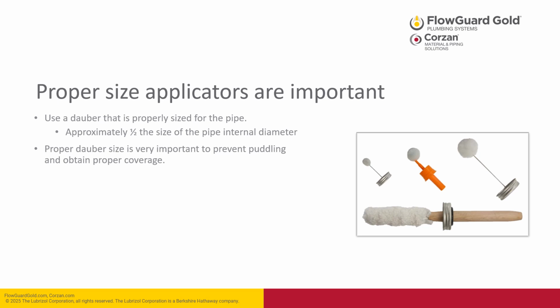The use of a proper size applicator is extremely important. You will want to use a dauber that is properly sized for the pipe. That means approximately half the size of the pipe's internal diameter. So if you're solvent cementing 1-inch pipe, you'll want to use a 1/2-inch dauber. If you're using 4-inch pipe, you'll want to use a 2-inch dauber. Proper dauber size is very important to prevent puddling and obtain proper coverage.